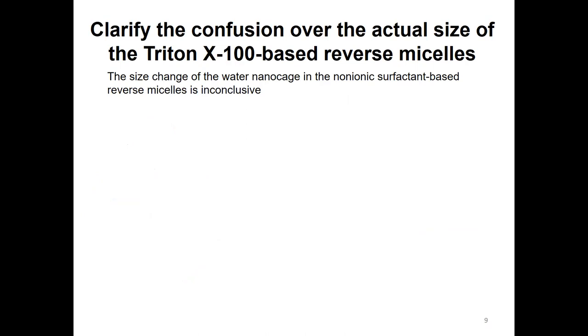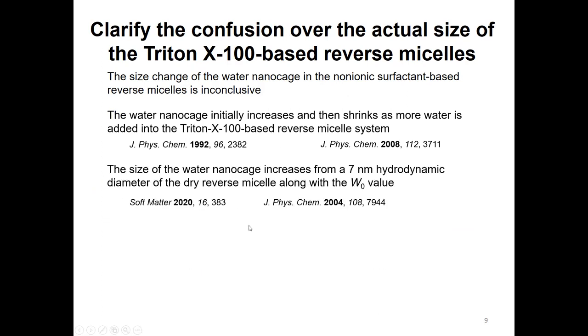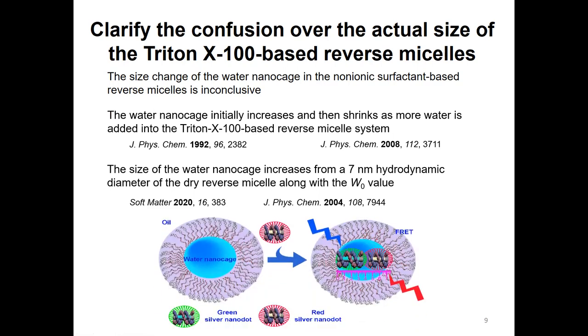When people study this, they also find something inconsistent. One thing people expect is that when you add more water into the reverse micelle, the size of the nanocage should increase. But in this paper, they mention that as you increase the water content, the size of the nanocage first increases and then shrinks again. But of course, some people say it will increase continuously. So which one is true? We try to use silver nanodots, placing them into the water pool to form a FRET pair. From the FRET efficiency, we know the distance between donor and acceptor, and we know the size of the nanocage.